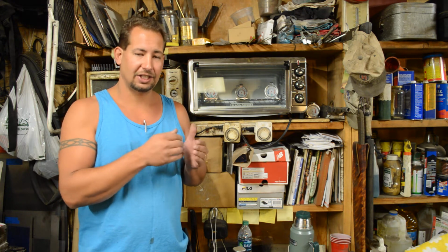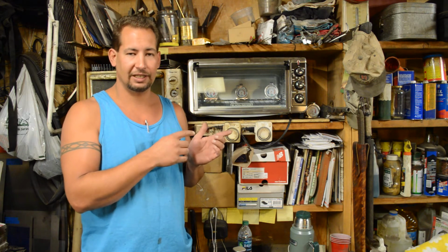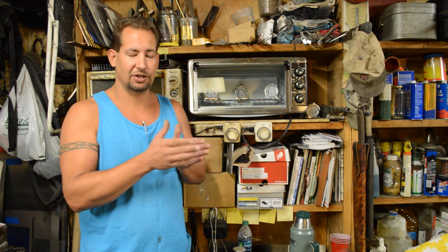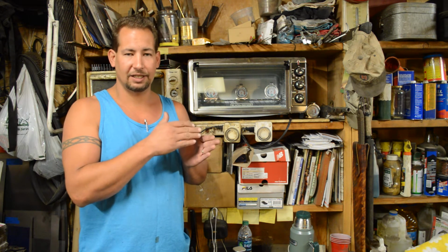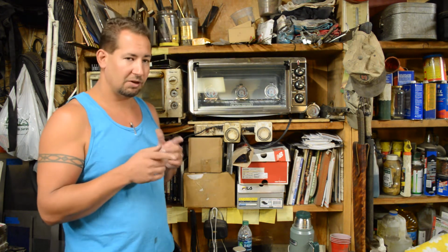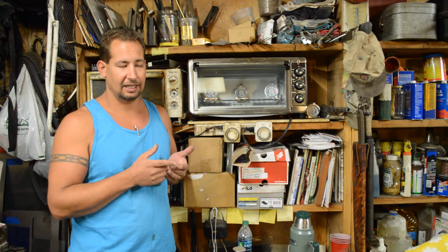You find that through doing edge deformation tests, which is the brass rod test, only you push it farther until you push the edge to failure. Note how that edge fails, decide how you want it to fail, and then adjust your tempering temperature to adjust the point of failure in that blade. So if you want the blade to be a little bit chippy, you use a lower tempering temperature. If you want the blade to be a little bit softer so that the edge deforms rather than chips, then you would raise your tempering temperature. Okay, so that's what we're after when we're tempering a knife blade.